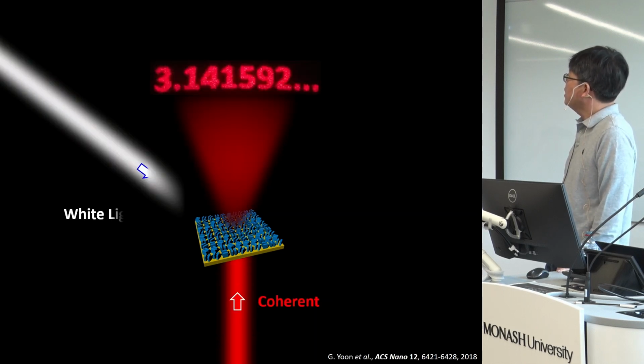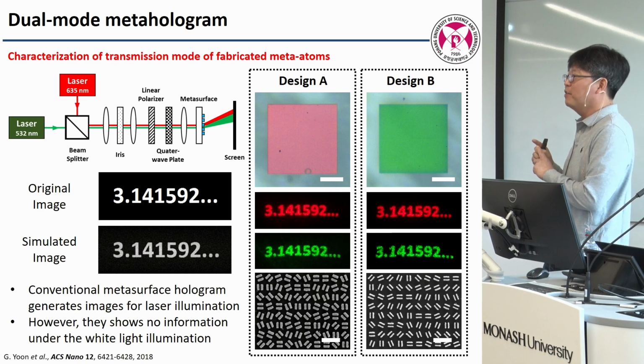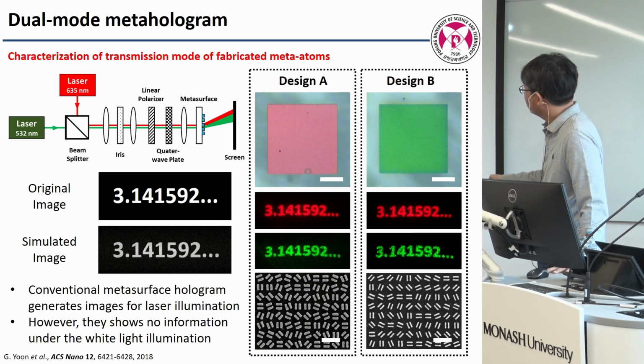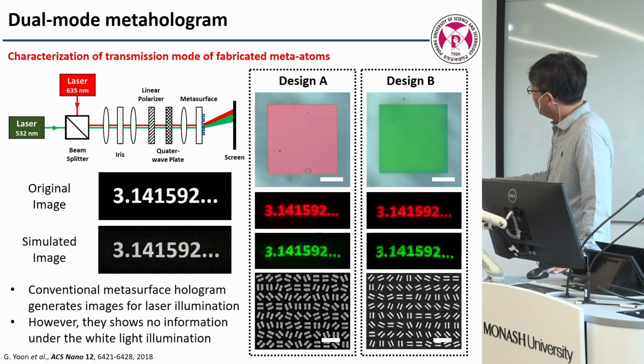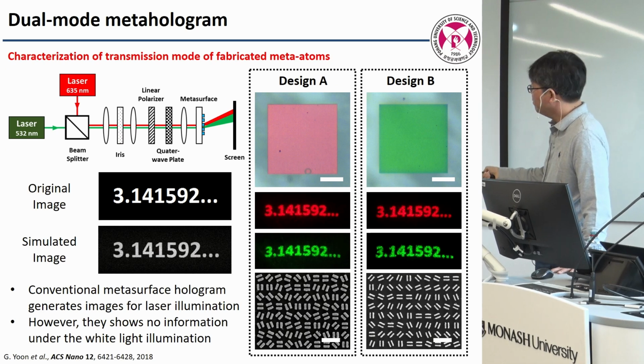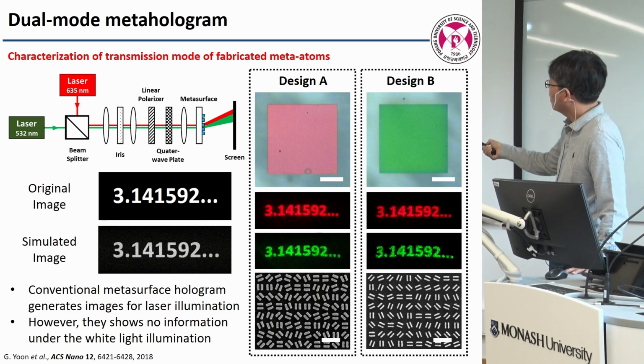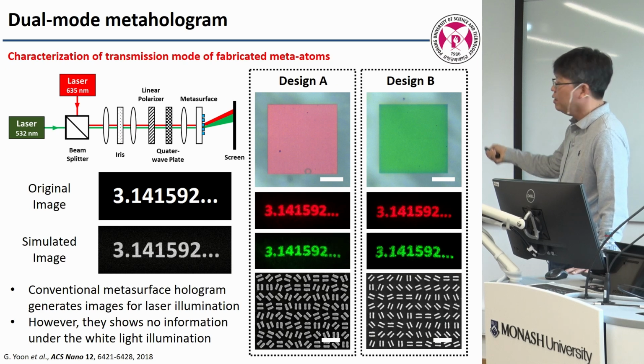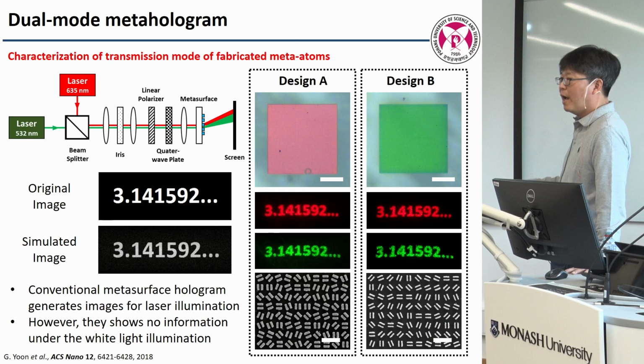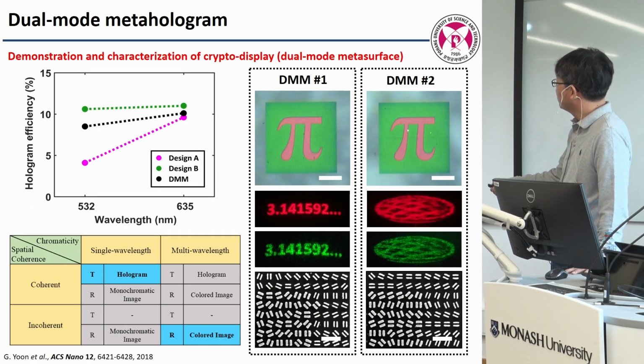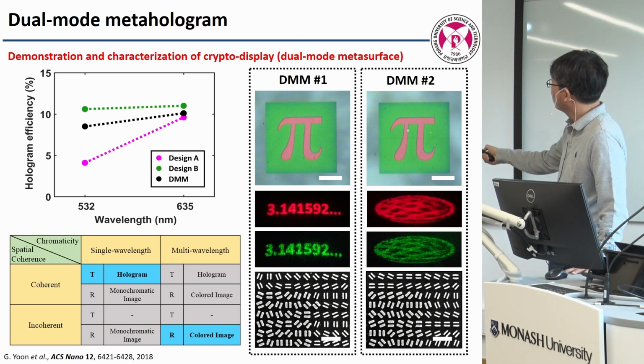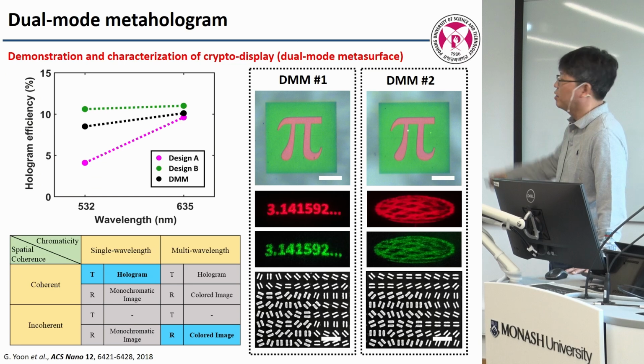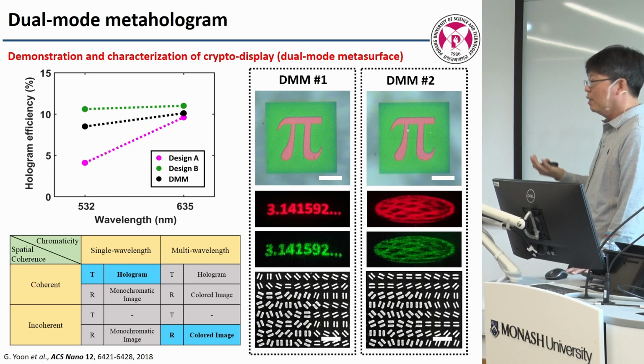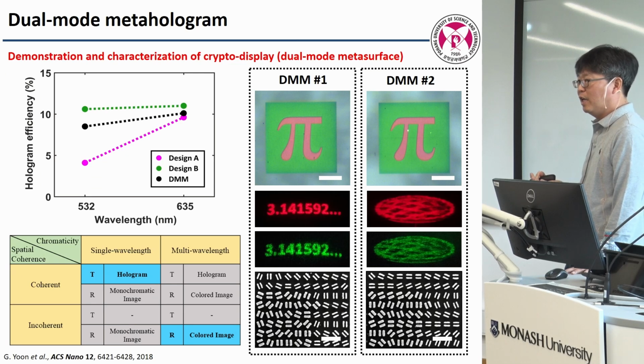So now this is a combination of amplitude control and phase control, very simple engineering. These two devices are the same in terms of hologram because the rotation angle of the unit cell is the same. So the geometrical phase control is the same, so you can see the same hologram here. But in your eye, the color differs: the fatter one is red, the thinner one green. So, keeping the angle the same, you will see the same hologram. But the fatter one becomes red and the thinner one a green background, so you have a different image. So we can control amplitude and phase simultaneously. Not 100% independently, but we can control them somehow.